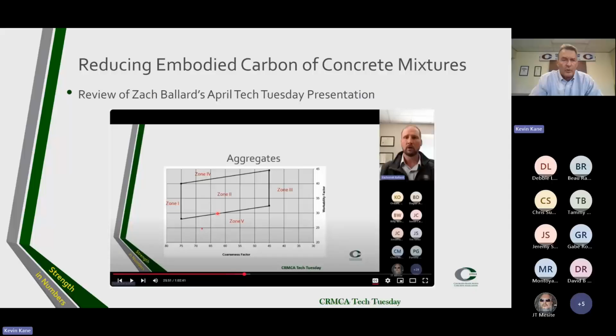And then these are some of the tools that Zach talked about we could use. This is the old coarseness factor and workability chart that Shilstone developed many years ago. And when you plot your combined gradation of your coarse and fine aggregate, you ought to be living in this zone 2. If you can make concrete in zone 2, you're going to be okay. If you're up here in zone 4 or zone 3, you might have some issues with your concrete. So you want to use these tools to get the right proportions of aggregate.